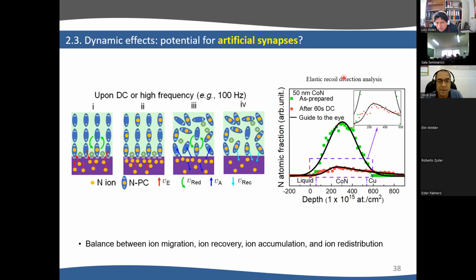This is a hypothesis, but we already did some elastic recoil detection analysis, which is a technique that gives you an idea of the nitrogen profile across the depth of the film. If the profile is symmetric, it means that the nitrogen content is more or less homogeneous. If it's asymmetric, it means that the nitrogen content is not homogeneous, that nitrogen is accumulated at some height. And here you can see that the as-prepared film nitrogen profile is symmetric, but it becomes asymmetric when we apply voltage. So this seems to indicate that there is indeed nitrogen accumulated at the interface.